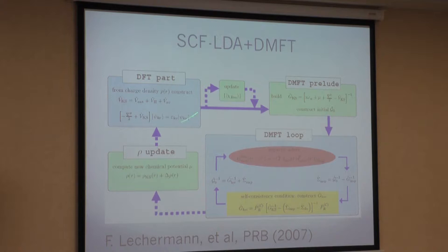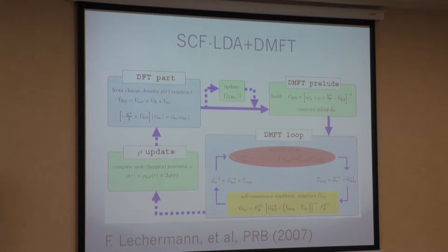So, this is a pictorial view of how the many-body LDA+DMFT package looks: you have a DFT part, a DMFT part, a projector, and you go back and forth to the correlated impurity solver. The main progress is realizing that for D electrons — 5 d orbitals — or F electrons — 7 f orbitals — you can already do quantum impurity simulation thanks to new methods. Rubtsov invented continuous-time methods and so on.